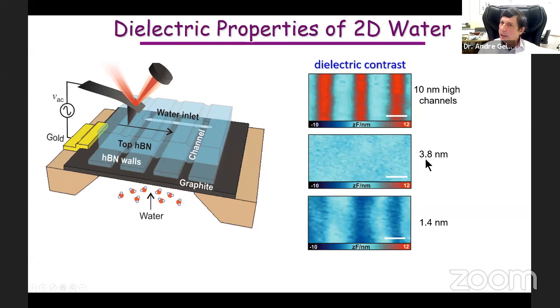Then when we go to smaller channels, about 10 layers of boron nitride used as a spacer, all contrast disappears, despite us being sure that water is in those channels. Using this trick I described, we don't see any contrast. And then we go to even smaller channels and see, after water was put inside, we get a negative contrast. So water gives you less dielectric susceptibility than boron nitride.